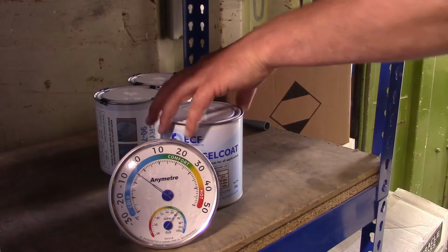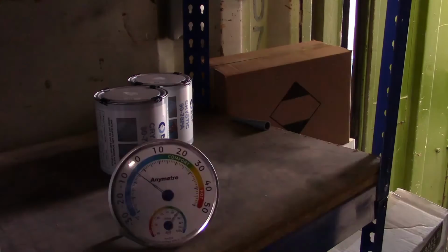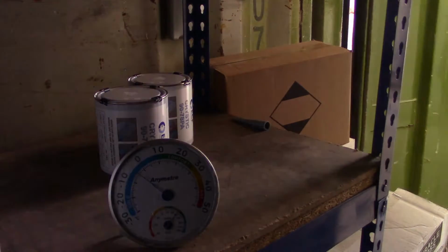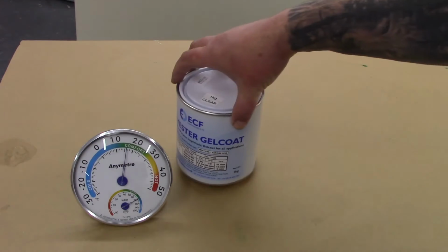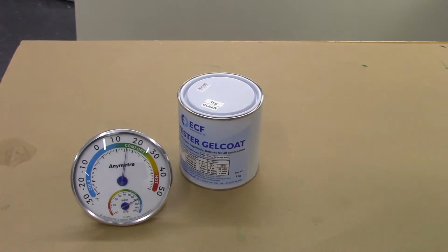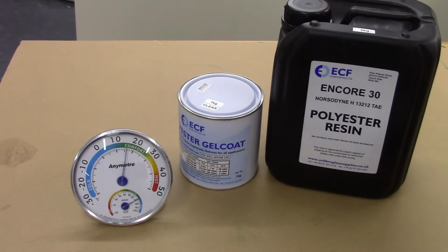If your materials and mould are coming from a cold storage area, then it's important to condition these also, between approximately 15 and 20 degrees C, 24 hours before you plan to use them.